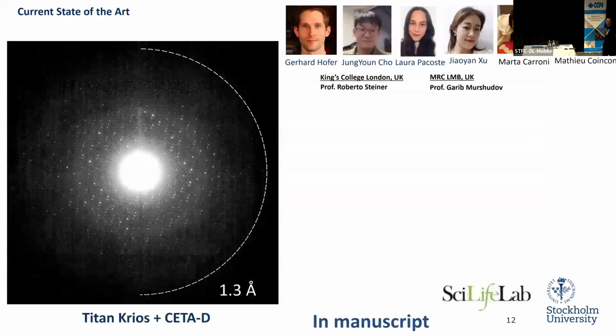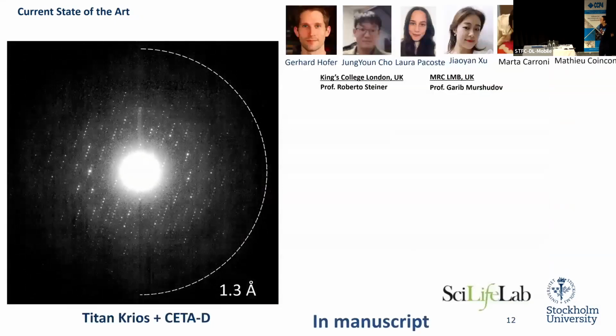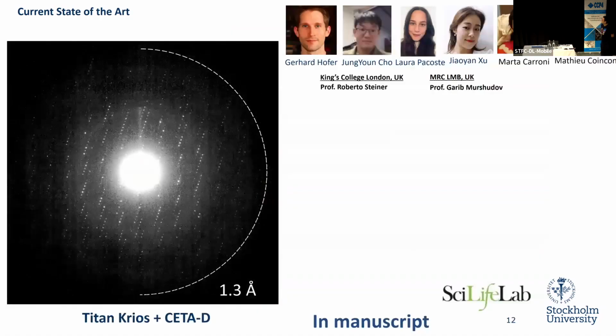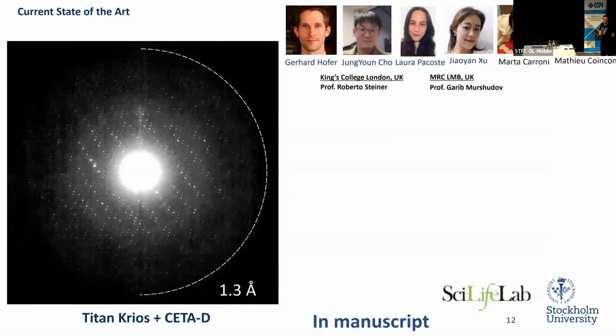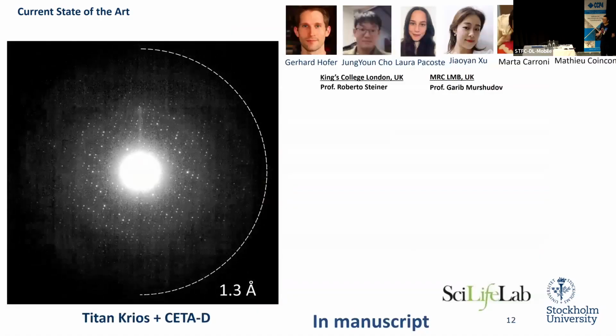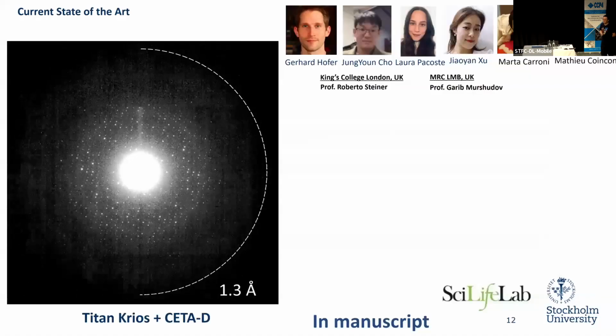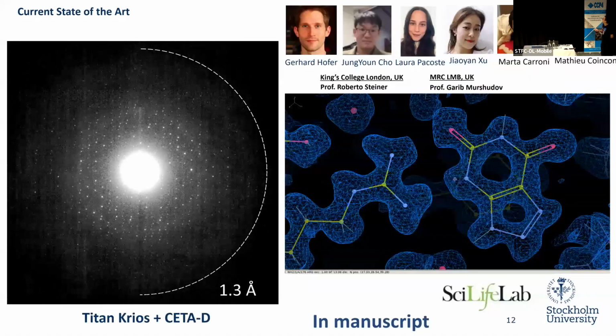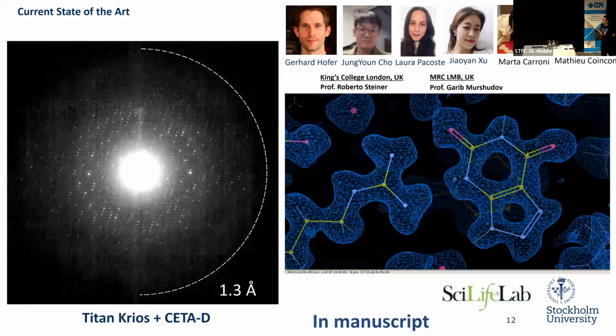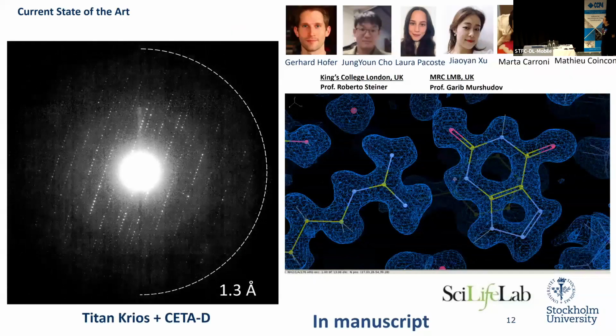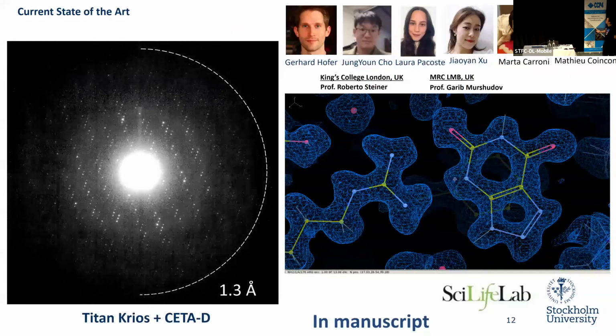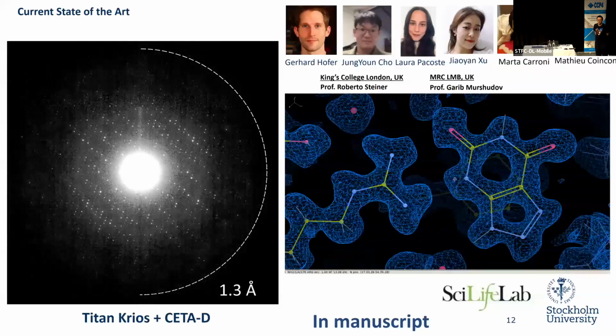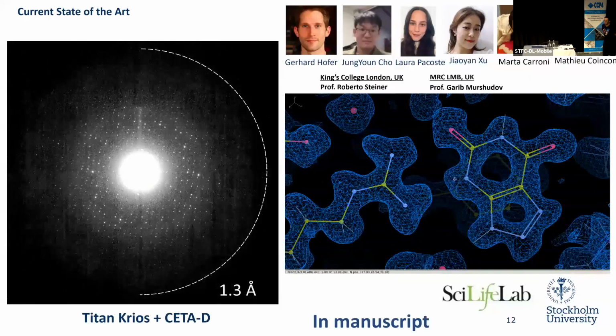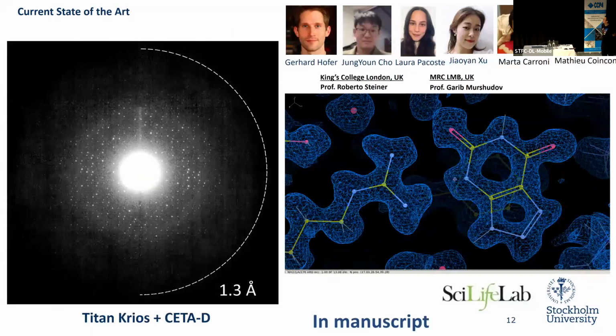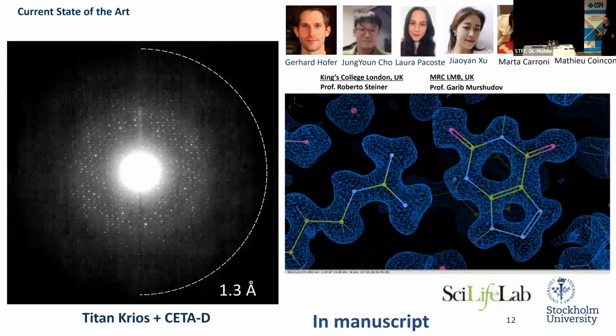Right, so this is one of the examples he did recently. It's a non-model protein, and the resolution can be very high because we optimized the size of the crystals and the packing as well. And this is the map that came with this kind of data. So this was very nice. Comparing to X-ray, for the same structure, X-ray had a resolution of around 1 angstrom. So we are still a little bit behind, but I think we are getting quite close in this way.